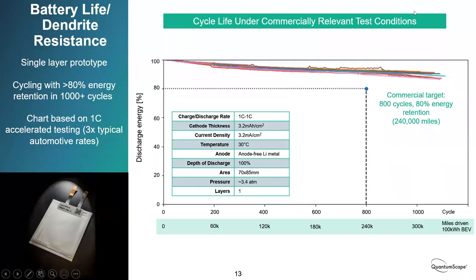I've got a little bit of data just to show you how the system performs. This is a cycle life chart for these solid state lithium metal batteries. What we're showing here is the retained energy versus the number of full cycles. For reference, we've shown the expected total number of miles that you might get with this system. The assumption here is that it's a BEV, a full electric vehicle with about a 300-mile range, so each cycle represents 300 miles of driving. We think the commercial target is about 800 full cycles, and that translates to 240,000 miles. So, pretty long life for the car.